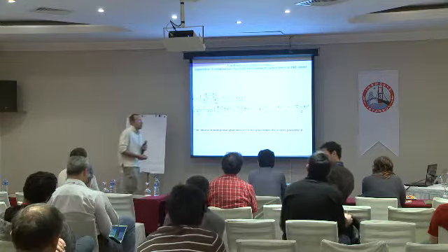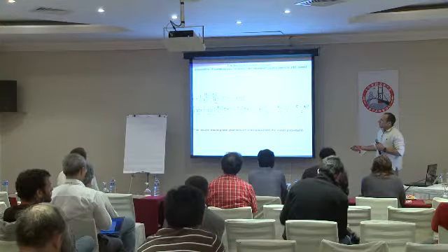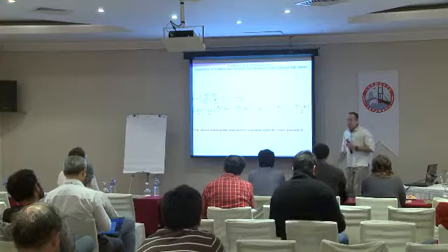First, let us take the London limit in this two-component model, and let us extract from our two-component London model the gradient of the phase difference. These are the phases of the complex scalar fields. In that case, you can recognize something like a gradient term of a Gross-Pitaevskii functional. There is no coupling to the vector potential in this combination of the fields.